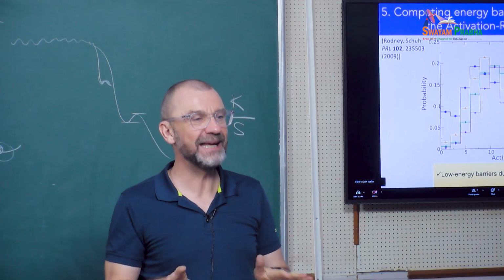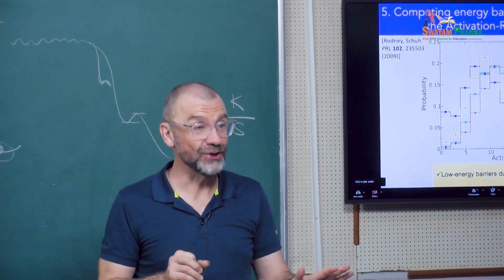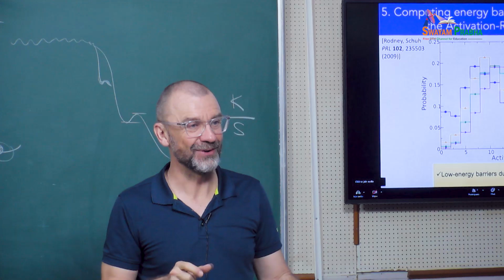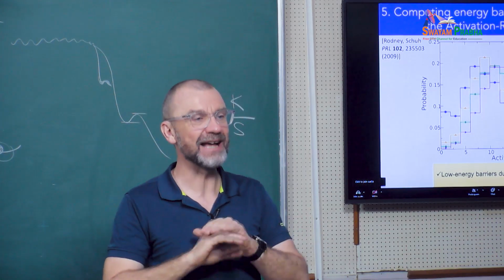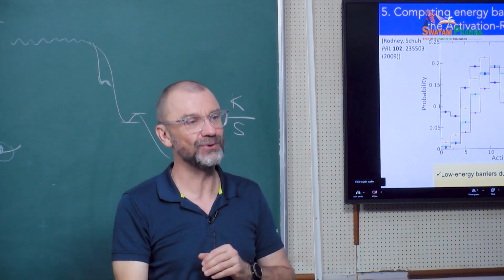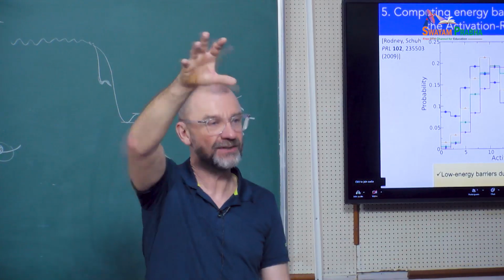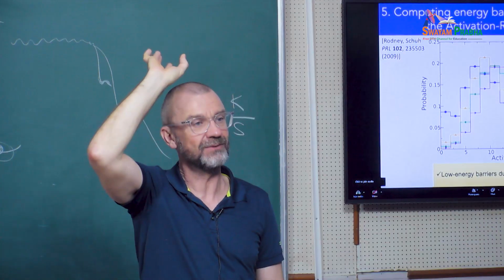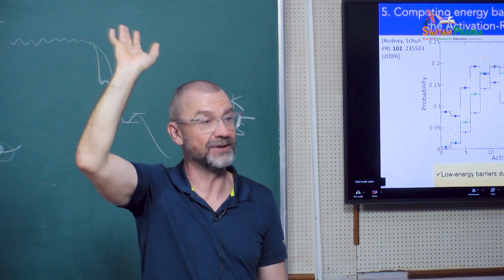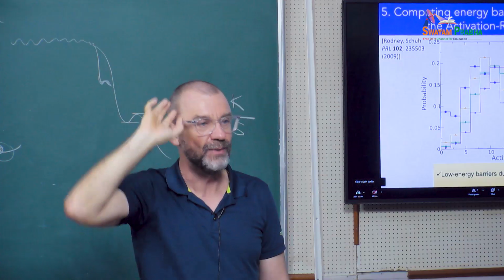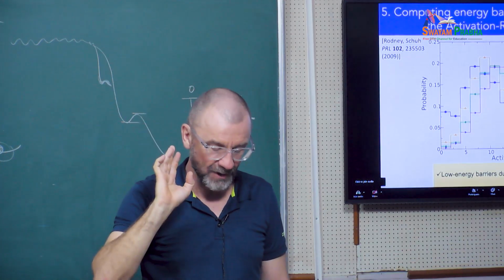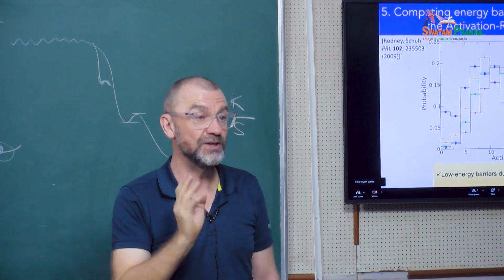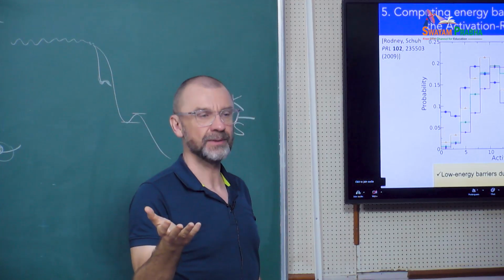So we cannot make any prediction of kinetics, for example. They will be extremely accelerated in our computer compared to experiments because we start from glasses that are very, very badly relaxed. So they still evolve very, very rapidly on human timescales. So we cannot make quantitative predictions, which means also that we don't care about the interatomic potential.